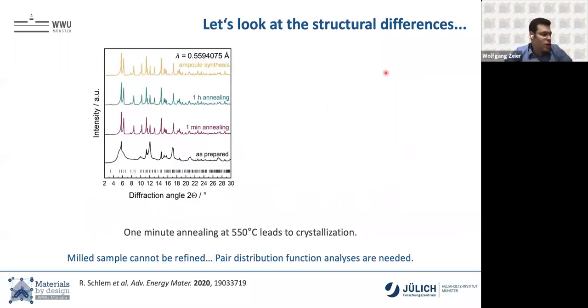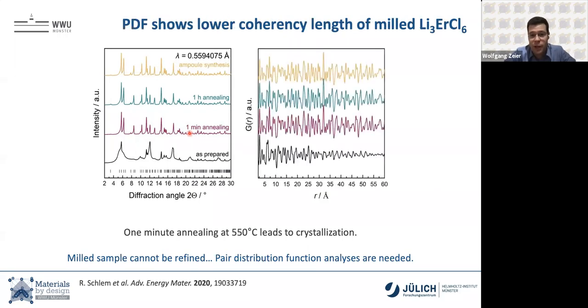Well, with structural chemists, we usually try to stick everything in a beam and see what structure comes out. The problem is, if you ball mill precursors, it's going to look like this. So this is nothing that we can actually refine in Rietveld refinement. The crystallized ones we can. 1 minute annealing, it's crystalline, that's remarkable, but not really part of this part of the story. So this is something where we can solve the structure.